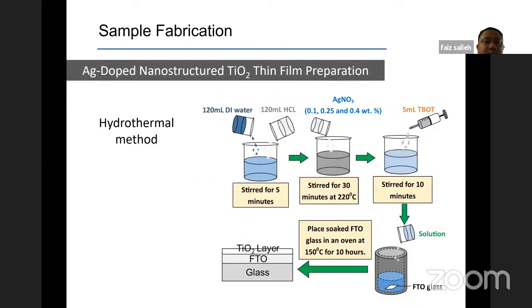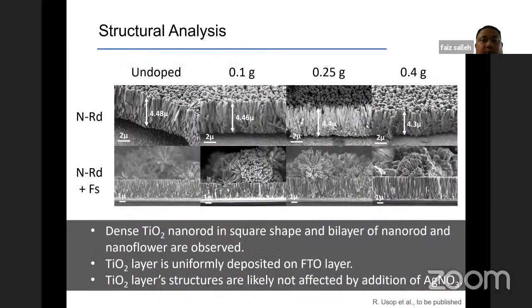So what we do is we dope the nanostructured TiO2 thin film with silver, or Ag. We're still using the hydrothermal method, and then we change the composition or the weight percentage of the AgNO3, the silver nitrate, inside the fabrication process. So when we increase the weight percentage or the amount of doping, 0.1, 0.25 until 0.4 gram, we observe from the FESEM image, this above is the nanorod, the single layer, and the below one, one, two, three, four, is the B layer, which consists of the nanorod and nanoflower.